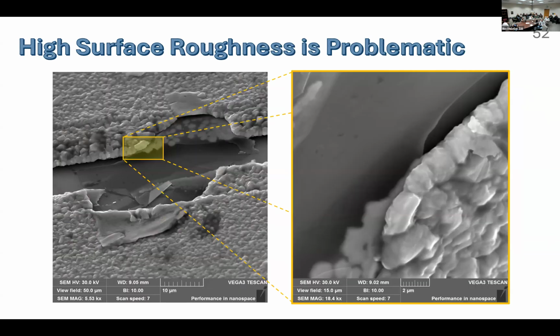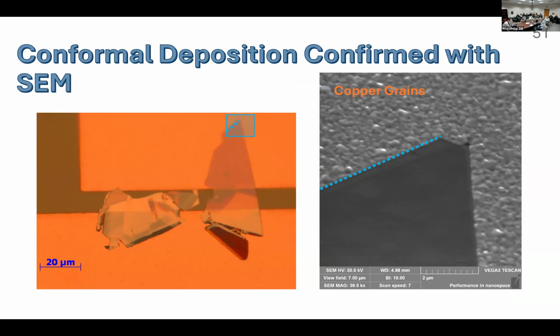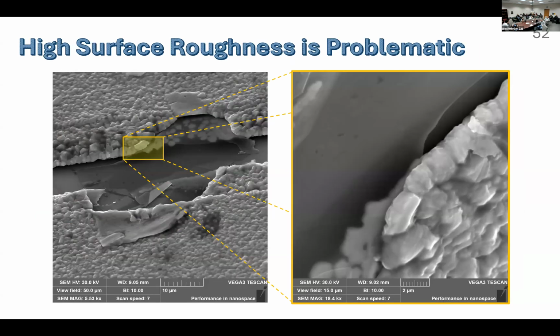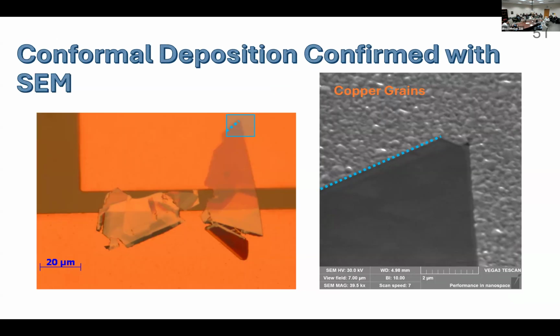Because I did this other measurement where I did it tilted. And when you see it tilted, you see that it's kind of sandwiched in between, as opposed to grown directly on top. I can show you more tilted images during the discussion. But that's how I was able to confirm that it was through the edges and not directly on top.